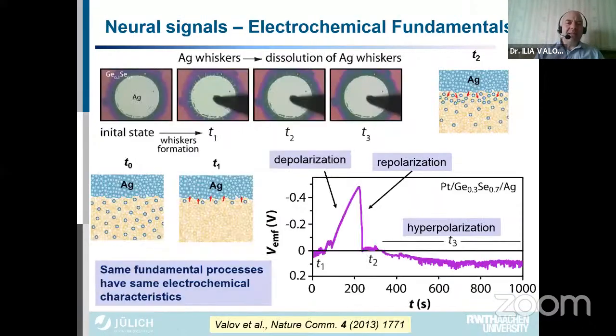Because the fundamental is the same, I'll show you the same response in an artificial inorganic system. So here we have silver electrodes, a memristive system, silver electrodes, germanium selenide as electrolyte, and platinum as a counter electrode. So initially you see this shade around the electrode. This is because silver is chemically dissolved into the germanium selenide. You see this is corresponding to this situation. So we have silver ions which are dissolved within the electrolyte.